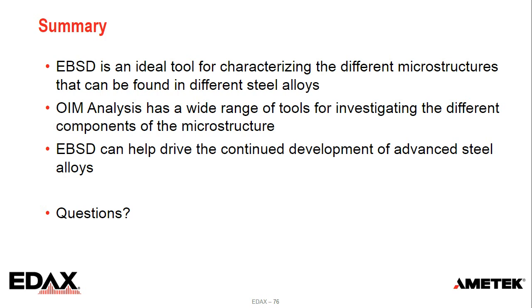The thing with EBSD to remember is we're a surface measurement technique. So when we prepare a surface, we're looking at a free surface, and that can also cause some possible relaxation and transformation, whereas XRD will look at a volume. So when you're comparing measurements from different techniques, it's important to know how they work, how they sample, and what the effects can be, because you very rarely will get a perfect one-to-one comparison. We did a lot of work looking at retained austenite, both true retained austenite versus synthetic retained austenite, where it was pressed together and wasn't transformed, as a sort of phase analysis, and trying to understand where some of these variants can come from, both with EBSD and other techniques.